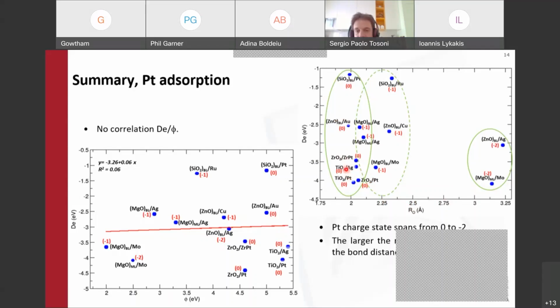The first group here are all the cases where platinum is bound as a neutral atomic species on the film. And the distance to oxygen is smaller compared to those cases where platinum forms a single anion. In turn, the cases where platinum acquires a -2 charge display a much larger distance to oxygen. This, of course, makes sense if you consider that oxygen is also an electron-attracting species. So, of course, you don't want to put an anion too close to it.